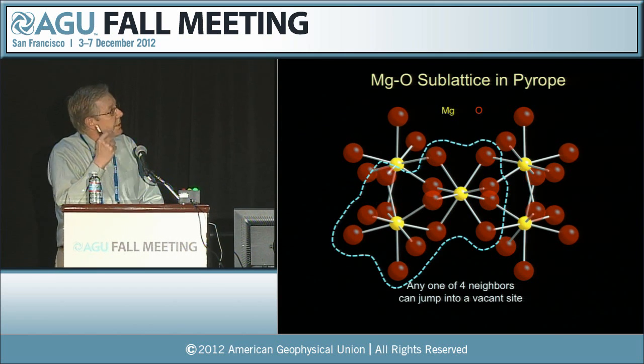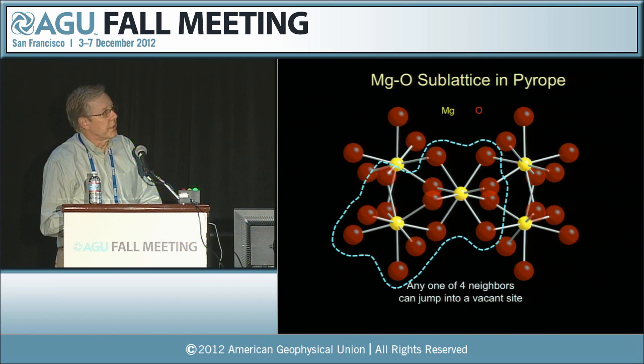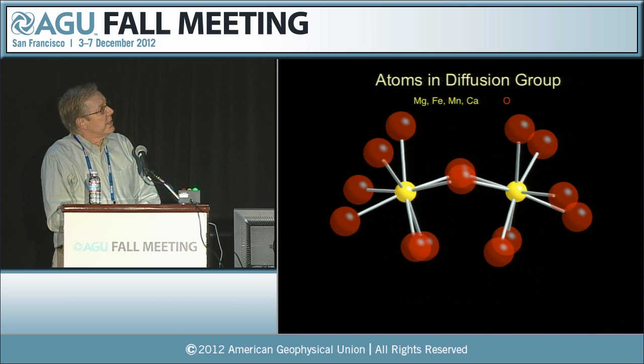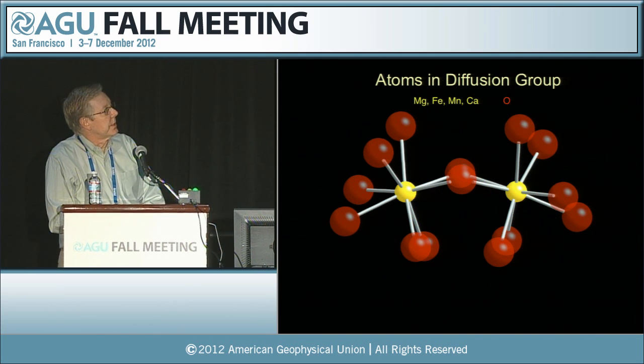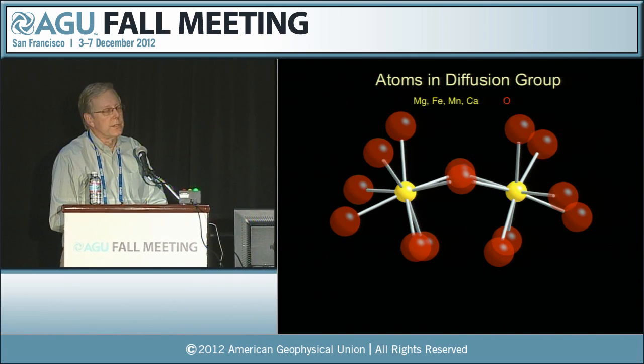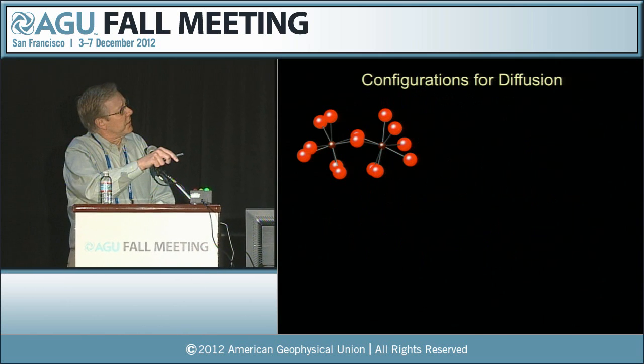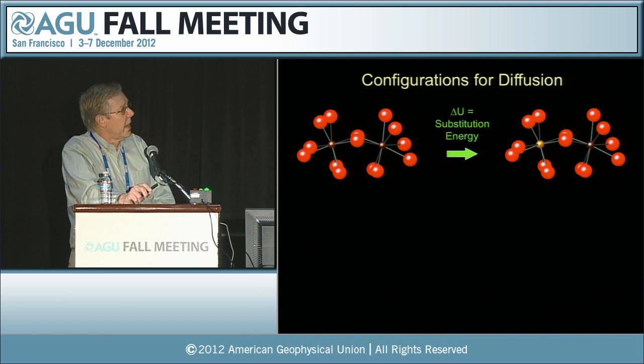And that means that we can just single out one pair of those dodecahedra for analysis of the energetics. So I call this the diffusion group. There it is. And this group takes on a variety of configurations during the diffusion process. If the initial state is the normal lattice shown here, the first thing that we have to take into account is the energy that is needed in order to substitute a different atom of a different kind into that same site. So I'll call the difference in lattice energy between those 2 configurations the substitution energy.